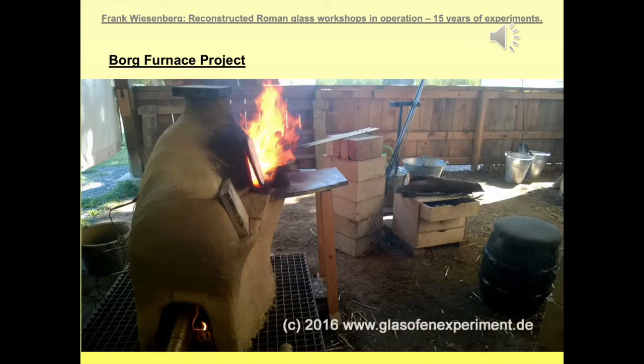Since 2016, I use this small glass furnace for a lot of demo days and research days, and also to teach myself and a couple of others some techniques of glass making. It's a very easy, very small workshop layout, and it works perfectly. It's very fuel efficient. It delivers temperatures up to close to 1200 centigrade. The problem is just above 1180, 1200 centigrade, the daub seems to disintegrate. Well, that's the only problem.